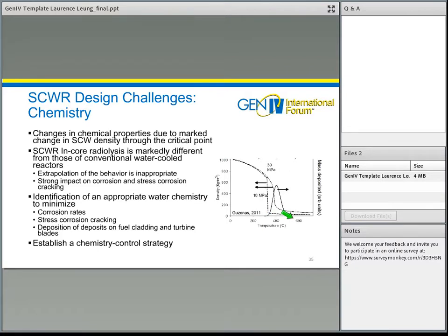But in the PWR, you operate and actually pass through the saturation point. For the supercritical SCWR at 30 MPa, for example, you still have a rapid drop in density at the pseudocritical point, but it's more or less not discontinuous because you don't have an interface change. But for the mass deposit in the fouled area, you can see it is very low at low temperature, and when you reach the pseudocritical point, the deposit mass drastically increases, and then when you go to high temperature, it decreases again.